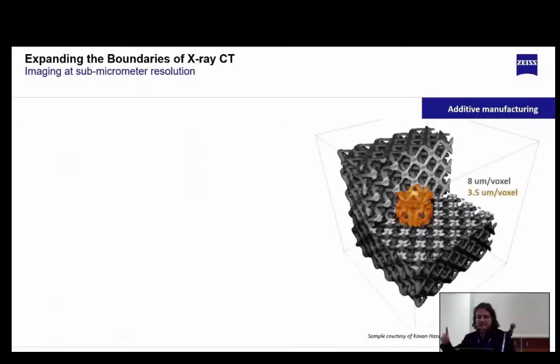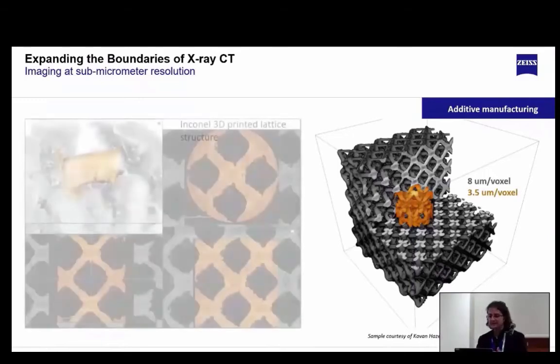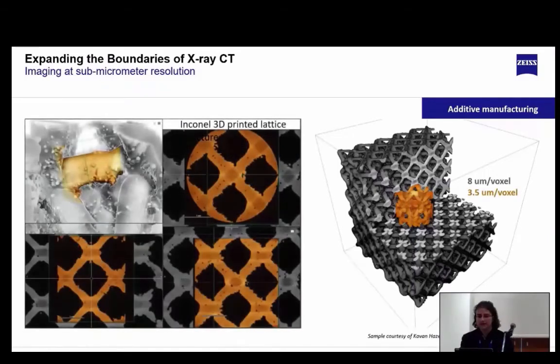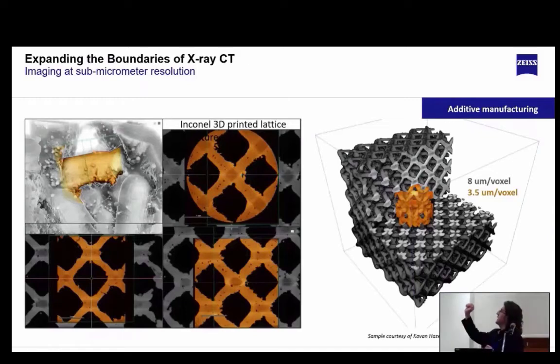It is one more example of a 3D printed lattice structure made of Inconel. And you see data of two different scans, one at 8 micrometers voxel size and a small region of interest at 3.5 micrometers voxel size. In the cross-sectional images, you can identify several interesting details of the build, such as internal porosity and the surface roughness around the joint features inside of the lattice structure.